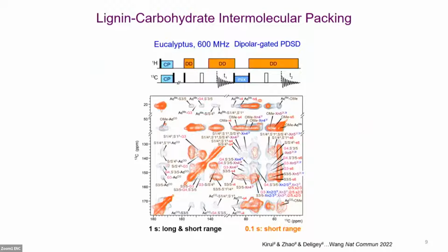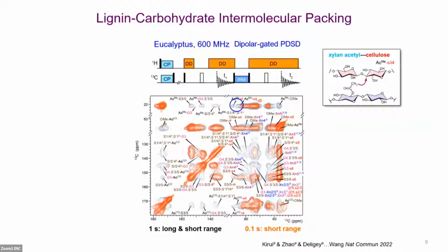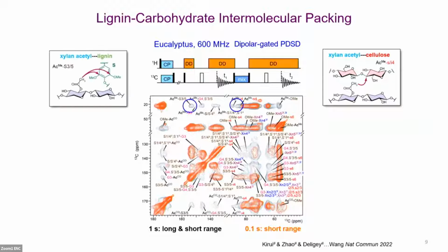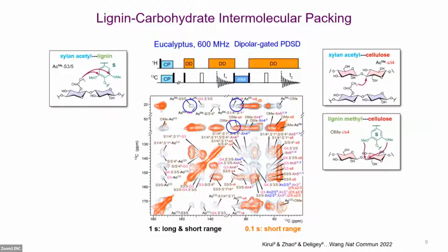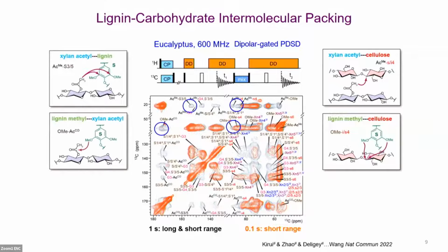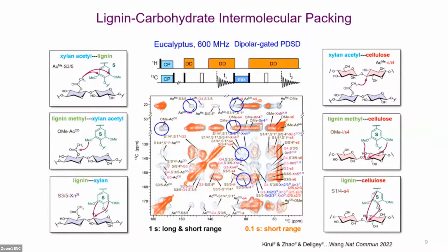Now we can try to find the lignin carbohydrate interactions. We use this Dipolar-gated PDSD pulse sequence. We selectively detect unprotonated carbon information and suppress the protonated carbon signals in the carbohydrate. Then we got this beautiful spectrum, and we can see hundreds of intermolecular interactions. For example, xylan to cellulose, xylan to lignin, lignin to cellulose, and lignin to xylan. All these different interactions, we can get the information, see which carbon is talking to which carbon.